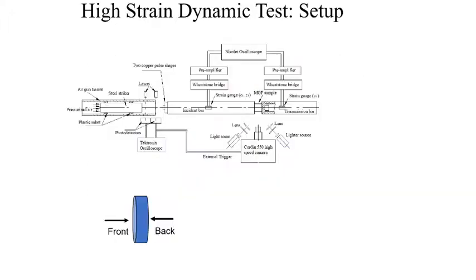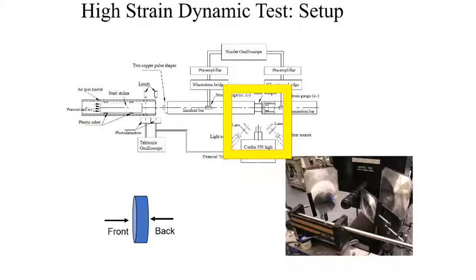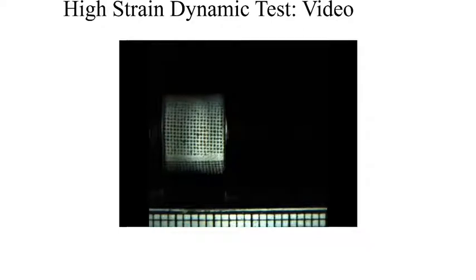So another thing that we have done, especially at UTD, is to use a high strain dynamic test setup like this. We put the material here and apply an impact, and then we use a high-speed camera to observe. In this case, we had a camera that could record up to 3 million frames per second, but here we needed 60,000 frames per second so that we can record that event. And this is where we recorded that. And this is the result of that impact.